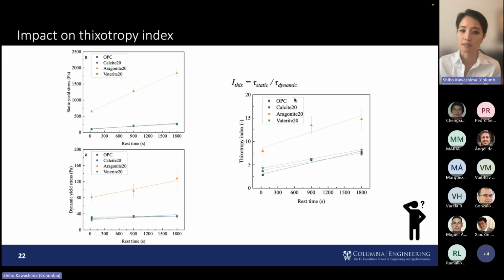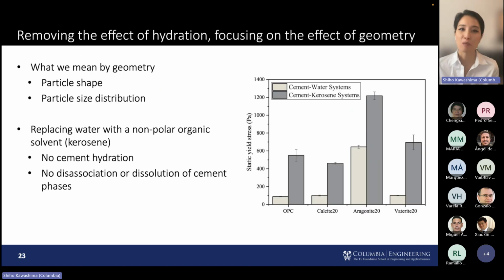And the ratio between this can be taken to be a thixotropy index, because the static yield stress gives you a measure of the structural buildup, and then the dynamic yield stress gives you a measure of the structural breakdown. And again, we're seeing the same trend, right? So it does increase dynamic yield stress, but relatively the increase in static yield stress is very, very significant. So aragonite is introducing this very interesting behavior, and we wanted to understand why.